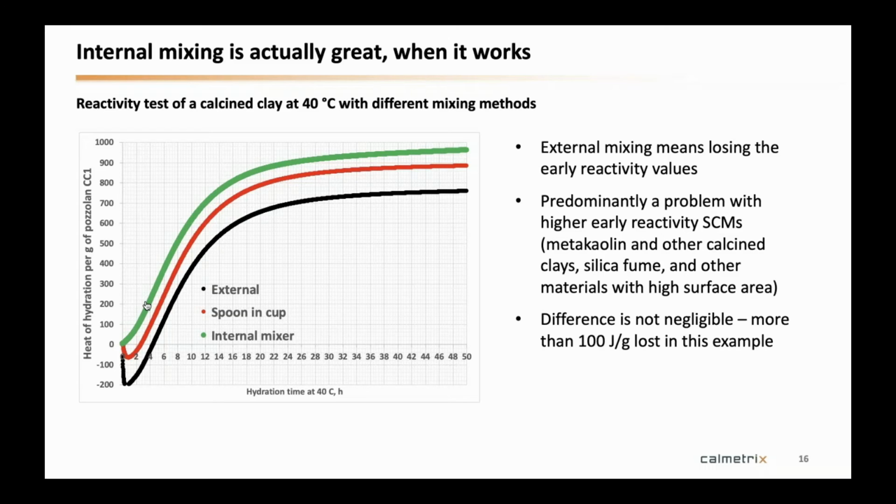However, it would not help having the reference also externally, because you would just introduce two variables in there. You would have a temperature gradient on the reference side and a temperature gradient on the sample side, and they're not necessarily the same, because one is being mixed, the other one isn't. And so you still have the unknown of what you actually get. It's the unknown part in the beginning, the overlap of different things, that makes it non-exploitable.